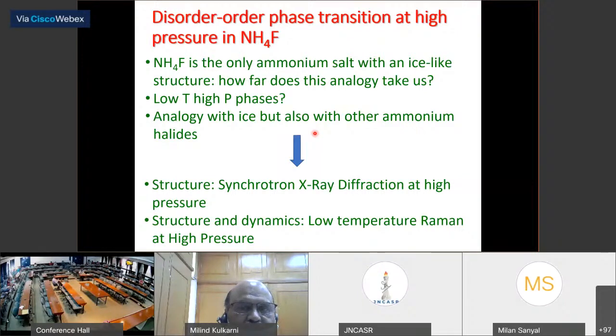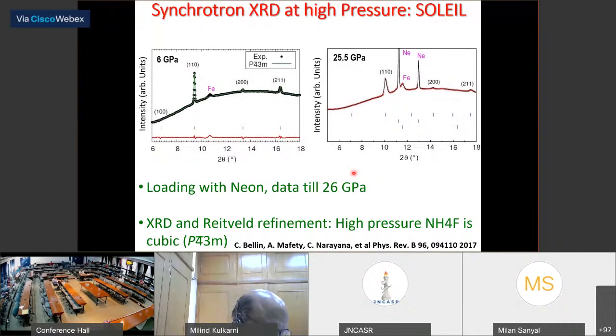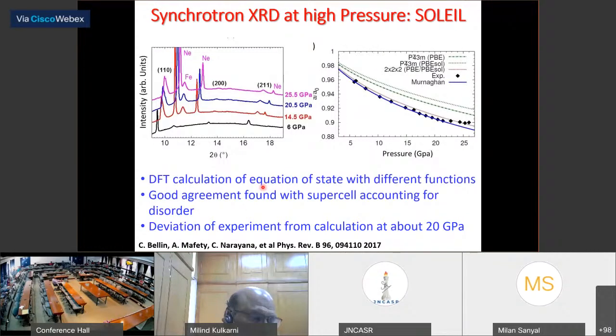Is it because of the tetrahedral nature? Does the low temperature, high pressure phase follow the ice-like behavior and other ammonium halides? So we did synchrotron studies at high pressure and temperature, as well as low temperature, high pressure Raman to look at this dynamics. When you pressurize at room temperature, it goes from a cubic structure into a high pressure cubic structure, remaining in the cubic structure itself.